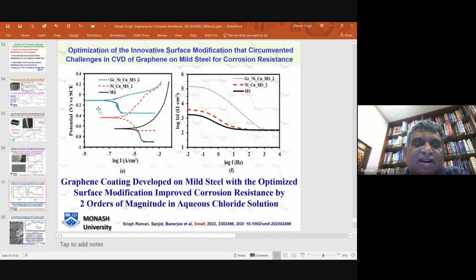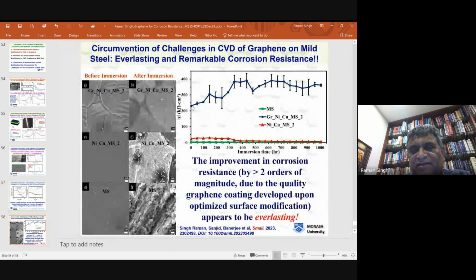As you can see here, that graphene developed on nickel that was plated on copper, and copper was plated on mild steel. So graphene coated mild steel gave very good corrosion resistance. As you can see, again, couple of orders of magnitude superior. Whereas without graphene, we didn't have much improvement. And that is what is shown in the polarization plots or in the EIS plots. And that graphene gave very good corrosion resistance.